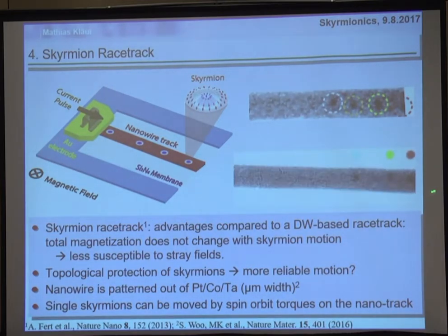And we did that, and it kind of looks okay, they're rolling back and forth. However, if you look closely, we start with 5 skyrmions, and after a little bit of injecting current back and forth, we end up with about 2 skyrmions. So we lost 60% of our data. Some sort of technology partner was not terribly impressed, but we wanted to check where that comes from.